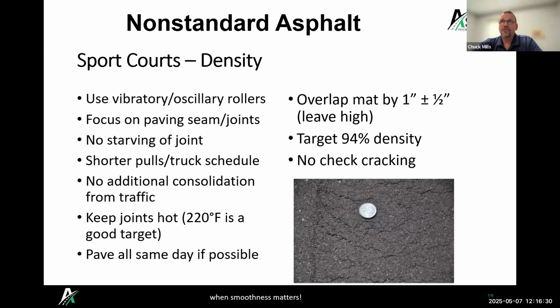Because we've got to make sure that we're getting all the density as we're placing it. We're not getting additional consolidation from traffic like we do with roads. Want to keep the joints hot. 220 degrees is a good target. Pave it all in the same day if possible, so that we're paving it quickly to keep those joints hot and better get density at those joints.